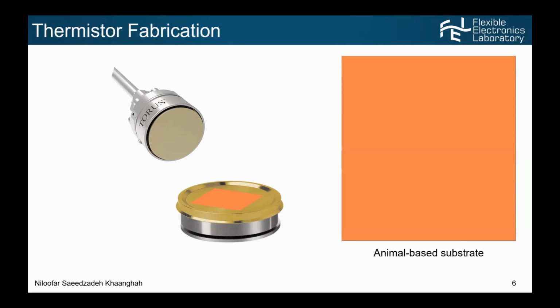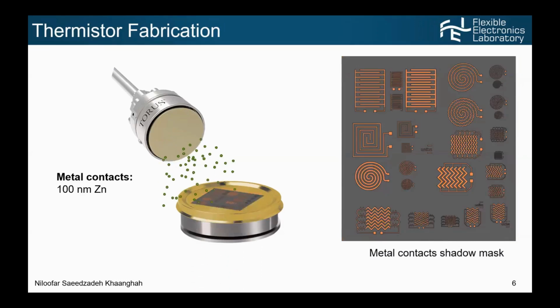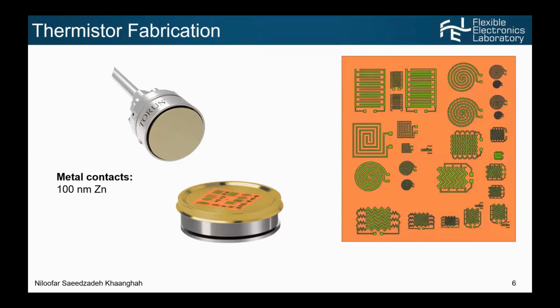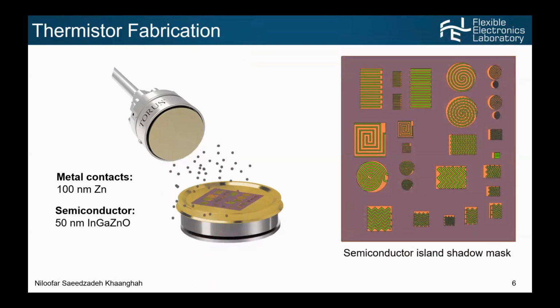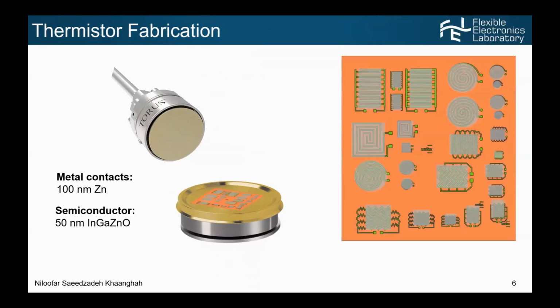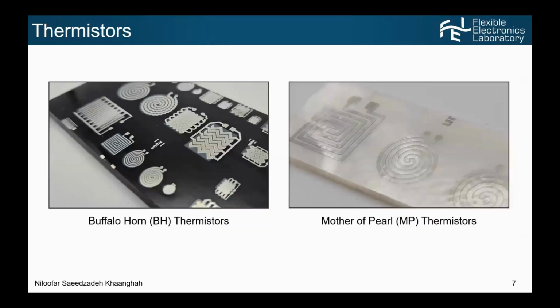We took these substrates one by one in the sputtering tool. To pattern the substrate with the metal contacts, I used a shadow mask and deposited zinc on top. But as we know, a thermistor has another layer, a semiconductor layer. So we used a second shadow mask and deposited indium gallium zinc oxide to connect the metal contacts together. This is the pattern of a thermistor with two stacked layers of material. And here are the fabricated thermistors on my substrate.